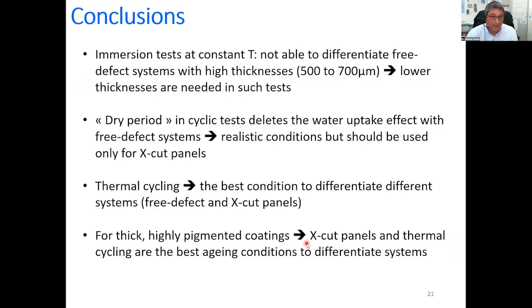So as a conclusion, it could be said that the immersion tests at constant temperature are not able finally to differentiate free defect systems with high thicknesses, up to 700 micrometers. So if we want to use this kind of test with a constant temperature, of course, lower thicknesses are needed to see an evolution of the barrier effect.